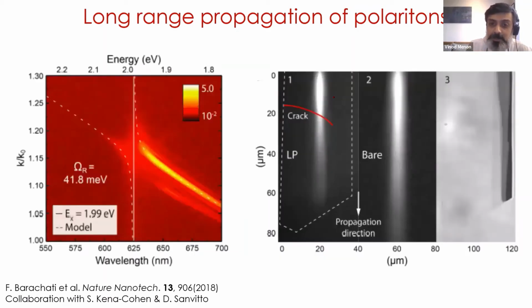And what we were able to show was that, so this is just your strong coupling data, but when we exfoliated this material, there was a very tiny crack in this material. You can see this in the optical microscope image. But if you look at the polariton propagation, it actually propagates through the system without any problem, because the polariton is very photon-like.